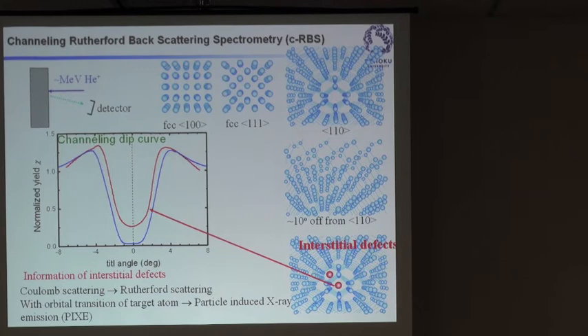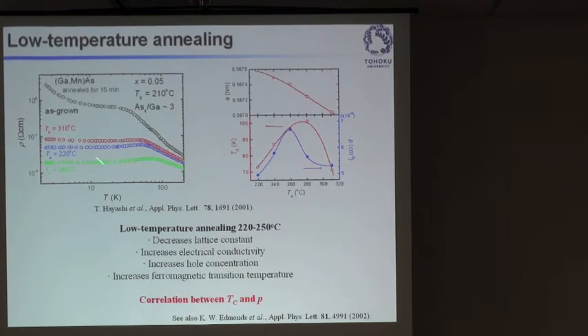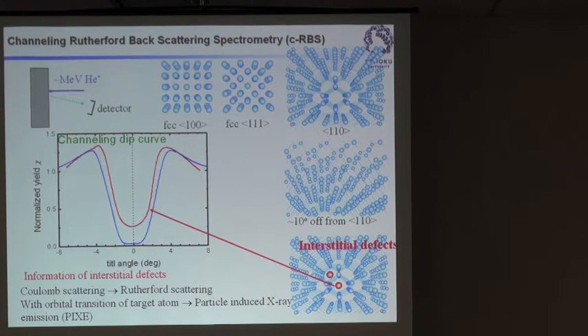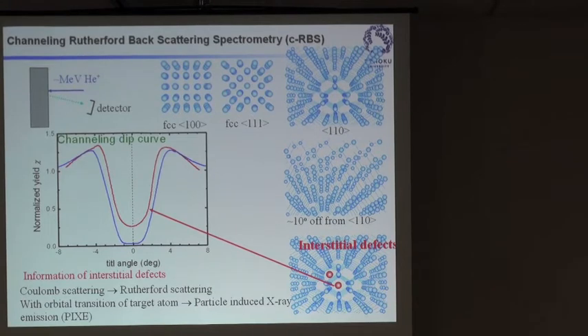And the reason for this increasing conductivity, or decrease in resistivity, is because we have manganese interstitial in the system, as well as manganese in a substitutional site. And this has been probed by Rutherford backscattering spectroscopy combined with particle-induced X-ray emission, PIXE, as many people call it, and by this channeling experiment. And at the same time doing this particle-induced X-ray emission, we can tell that manganese is sitting at the interstitial position.